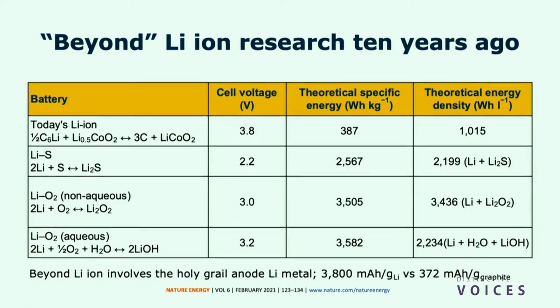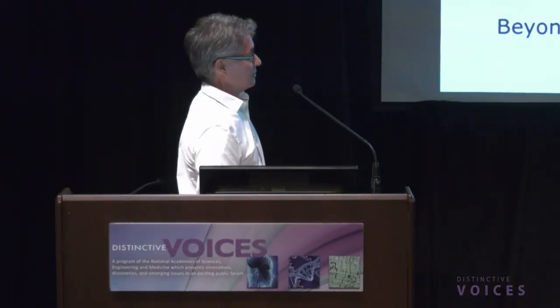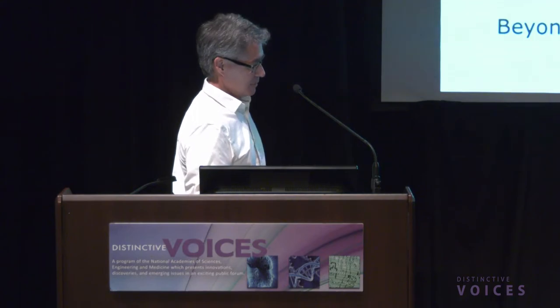So something about what's appealing about these technologies, again, if you look at cell voltage, this is the most important one. Theoretical specific energy, here's lithium ion. Lithium sulfur, wow, it's a huge jump in watt-hours per kilogram when you're reacting lithium with sulfur. Lithium oxygen, non-aqueous, again, an order of magnitude increase in specific energy. And similarly for lithium oxygen aqueous. So what really limits these technologies, they kind of came to a head, like I said, about 10 years ago.